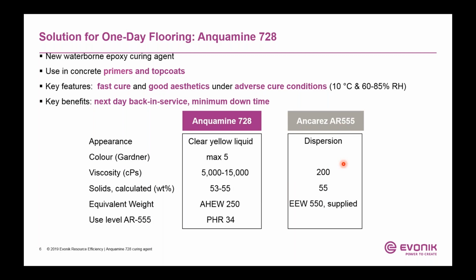The key feature of Anquamine 728 is that, in combination with solid resin dispersion AR555, it delivers ultra fast cure speed and good aesthetics under low temperature and high humidity. So the benefit is return to service the very next day at minimum downtime.